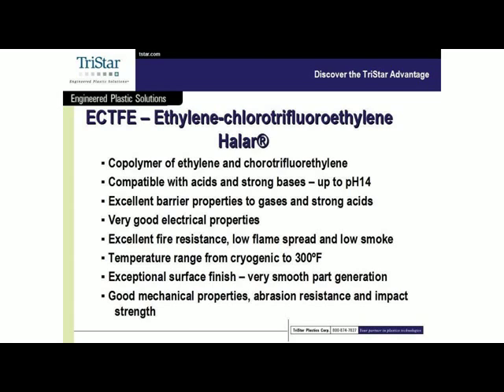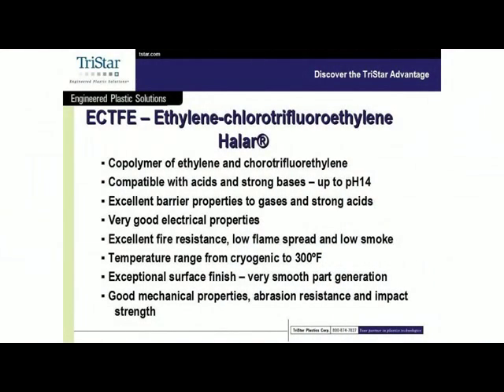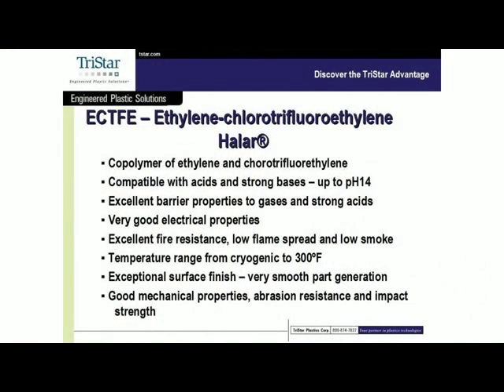It does not embrittle, and it does very well at holding its physical properties even at cryogenic temperatures. One of the other things about the ECTFE is that its natural finish, whether it's injection molded or film or compression molded part, is a very, very smooth material. It has very nice flow properties to it. So if you're looking for a part like a pump body or a fitting or something like that where you need a very good surface finish, this material tends to be the one that has the best finishes available to it. And finally, ECTFE has very good mechanical properties, good abrasion resistance, and impact strength.